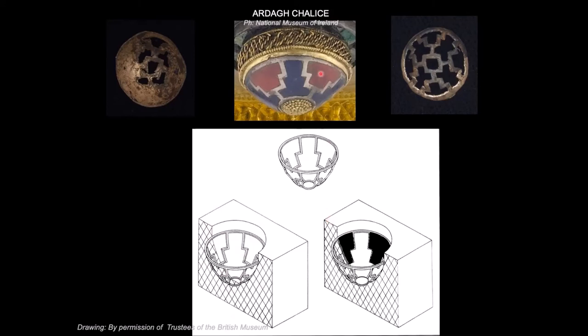They got the red glass, and the composition of the red glass was something you couldn't really heat up very much, because if you did, it turned a horrible greeny black colour. So they treated it a bit like butter. They softened it, and they put the little bits of softened red glass into the T shapes. Yeah, they are in the mould. This has been cut off here, but it's another T shape at the beginning of all, you see. But you mustn't let it overlap, because if you do, it'll show.